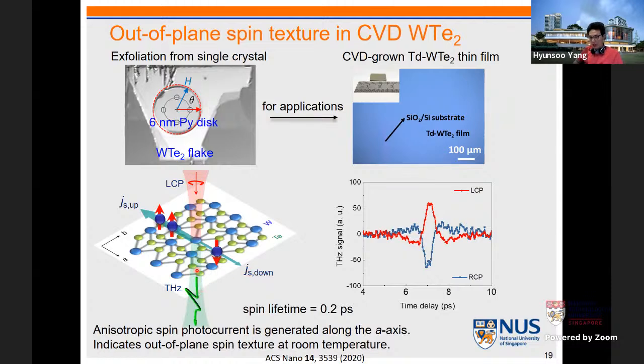Once we measure the emitted terahertz, we can look at the charge current oscillation phase. In the left case we see a positive peak, but with right circular polarized light we see a negative signal from the terahertz. That indicates the initial oscillating phase is 180 degrees shifted. That means the coupled spin, depending on the circular polarized light, is opposite. So this measurement suggests that there is out-of-plane spin texture at room temperature in this tungsten ditelluride material.